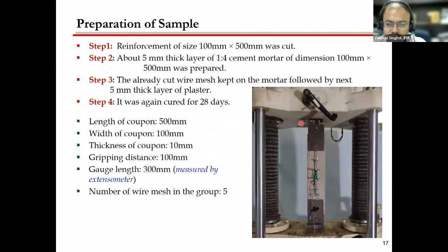So this is another picture from the test which we have done at IIT Patna. Here we have used a coupon of size 100 by 500. The reinforcement was also cut to that size. First, we took a 5 mm thick layer of mortar, and then the reinforcement is placed over it, and then another 5 mm thick layer of plaster is laid. Then you can cure it for 28 days, and it can later be used for the testing purpose.